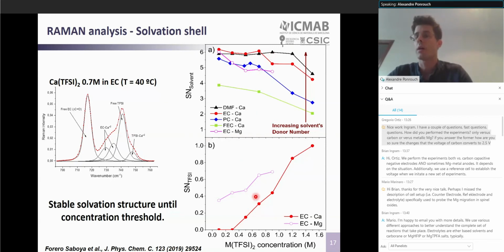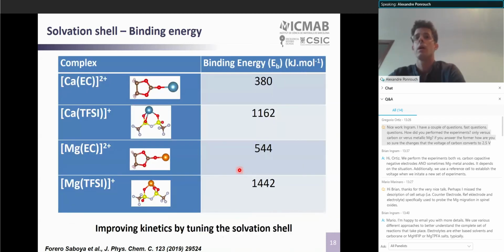When we compare now the calcium and the magnesium system, what we can observe is, as expected from the higher polarizing power of magnesium, we start to form contact ion pairs for the magnesium complex at concentration as low as 0.1 mol. So this is, of course, one thing that should be of concern when designing magnesium-based electrolyte. They are much more prone to form contact ion pairs.